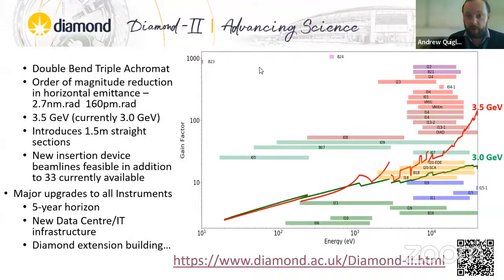Just to give a quick overview of what's going to happen, the new design is going to be a double bend triple achromat, and that will give an order of magnitude reduction in the horizontal emittance. So we'll get a much more coherent beam. As part of this, we're also going to boost the energy from 3 to 3.5 GeV, and when working at high energies in particular, this is going to be really beneficial, especially on the MX beamlines, where the gain factor we get from working at these higher energies means we get a much bigger output from the crystals that go on the beamlines.